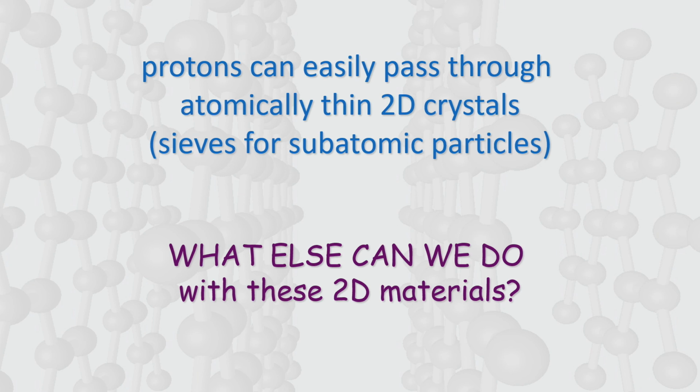Our lab deals mostly with studying what materials can deliver, what interesting properties could be there. One of the experiments which I think is the most fascinating which we have done is to take a vacuum chamber and cover its small window, several microns across, with a two-dimensional crystal, say graphene or boron nitride, and the vacuum withstands quite easily the pressure difference between vacuum and room pressure.